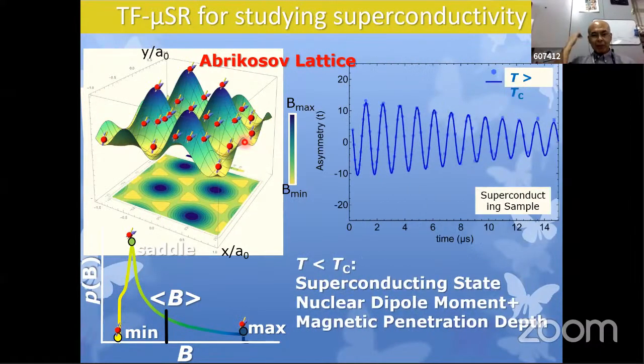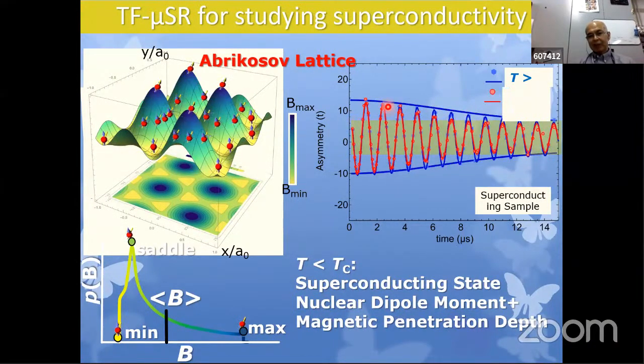Then what we can see is the normal state muon spin precession property. Okay, there is a very natural decay here. But in the superconducting state, due to differences in the Larmor spin precession motion, we can see a decrease of the polarization, like that, from blue to red. This is realistic data, so there are many factors why we see small differences, but we can definitely see differences, okay? This is how to figure out the superconducting state by MUSR.